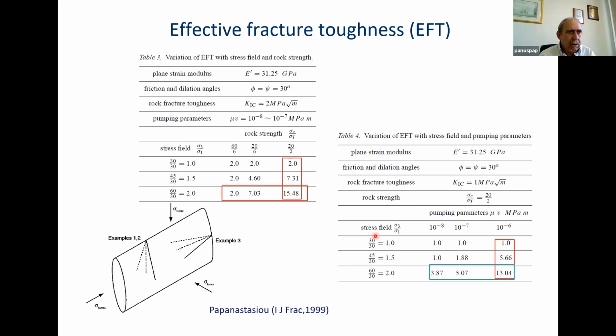In the second example, what we varied, we kept the same rock strength ratio, compressive to tensile, as you can see, and we vary the pumping parameters in the columns, and again, different stress field in the rows. Again, you can see here, of course, when we have high pumping rates, we get higher stress concentration and more plasticity, but this effective fracture toughness is particularly high when the stress field is anisotropic. That's the case when the front propagates vertically.